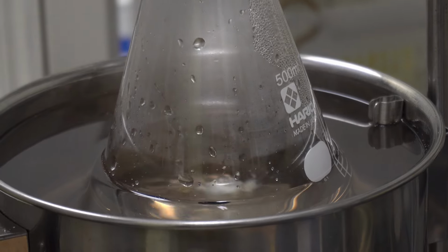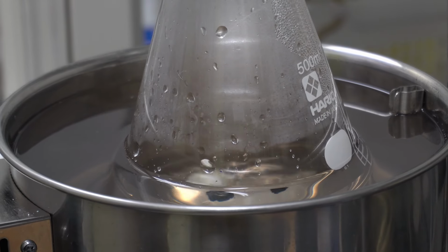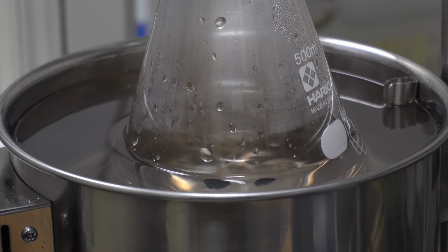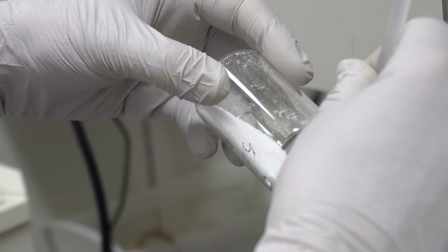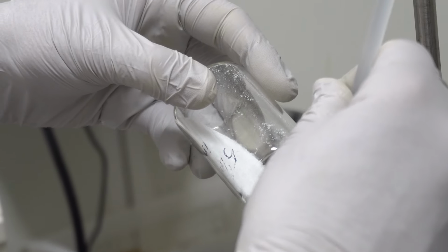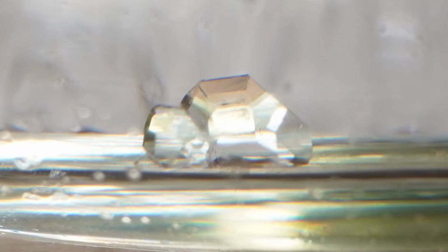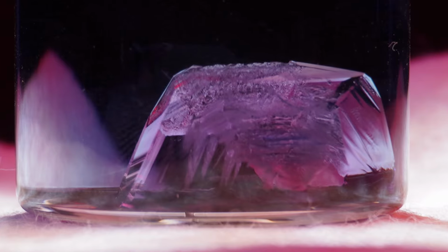But it was after this experiment that we got a very pleasant surprise. We decided to try and grow these crystals even larger if we could. So we made some stock solutions of saturated sulfates, of just the aluminium sulfate and then the aluminium chromium mix. But this time we heated them up and we added extra material. We added some extra sulfates in there and put a cap on the tubes and let them cool down. And within a few hours, we had small, single crystals at the bottom of the tube. And within a day, we had these large crystals.